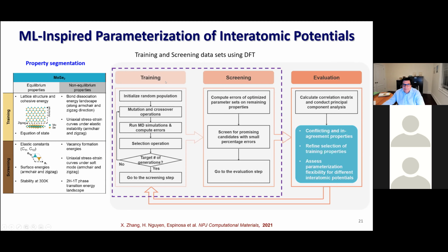Now, the scheme has three major components. The first one is training, which I will explain to you in more detail. So we are essentially looking for the constants in the force fields that best reproduce the DFT data. Then we do a screening for best candidates, and then we do a statistical evaluation, which is very helpful. So let me explain each one of these pillars. Well, I want to show you that we have a pillar with training, screening, and evaluation.